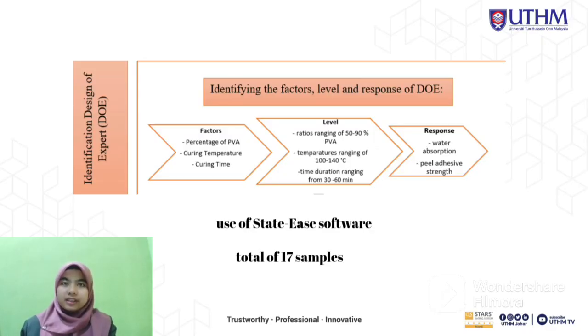Methodology. First of all, I will use DOE to identify the factors, levels, and responses. For the factors: percentage of PVA, curing temperature, and curing time. For the levels: ratios ranging from 50 to 90% of PVA, temperatures ranging from 100 to 140 degrees Celsius, and time duration ranging from 30 to 60 minutes. For the responses that I stated before: water absorption and peel adhesive strength. After calculating the factors, levels, and responses, there are a total of 17 samples that I will use as a reference to make the samples.